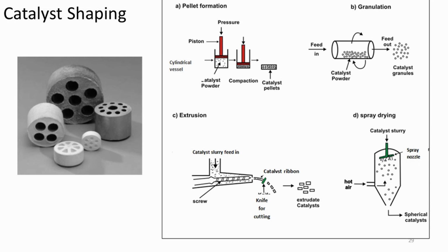Binders may be added to enhance the mechanical stability after material compression, and the important process parameters are the maximum pressure and the rate of pressure rise, both of which influence not only the hardness of the pellet produced but also the integrity of the particles inside. The process may cause crushing of crystals, shifting of crystal planes, and other effects of high mechanical stress. A further disadvantage of pelleting is that the porosity and pore texture of the final product can hardly be controlled. The figure shows that it is possible to press catalyst pellets with structured perforation such that mass transfer of reactants and products can proceed.